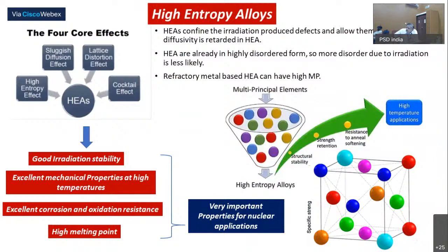Now, when you have such a high distortion effect, what you get is a very sluggish diffusion process. And if you have a very sluggish diffusion process, what happens? Now, that is where I wanted to show what irradiation can do. Whenever irradiation takes place, the Frenkel pair generates one interstitial atom and one vacancy. In conventional alloys, the vacancies remain in the same place. Interstitials diffuse very fast, and in the process, the remaining vacancies create a lot of problems, and that is the reason which modifies the structure of the component.